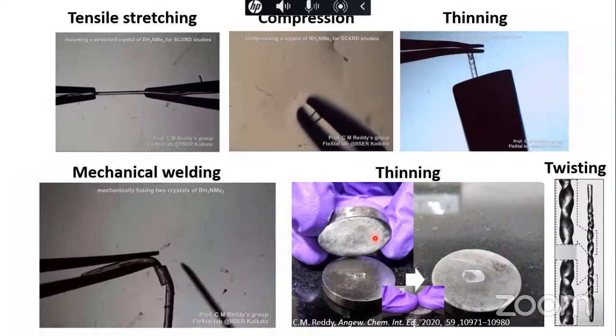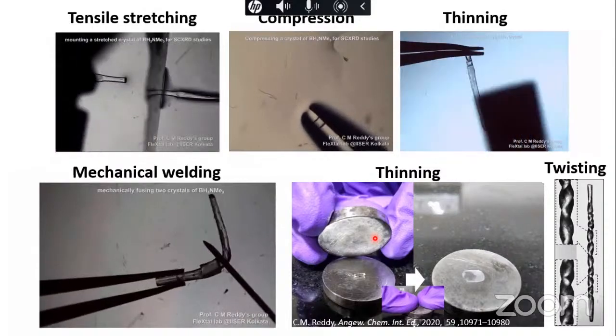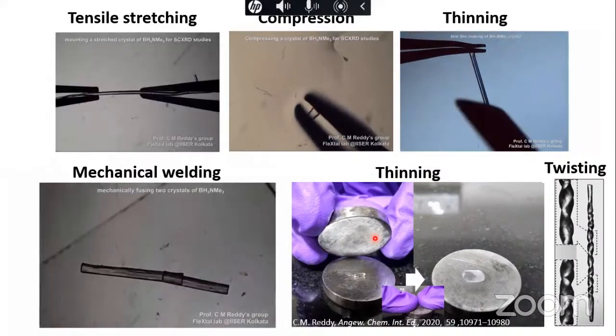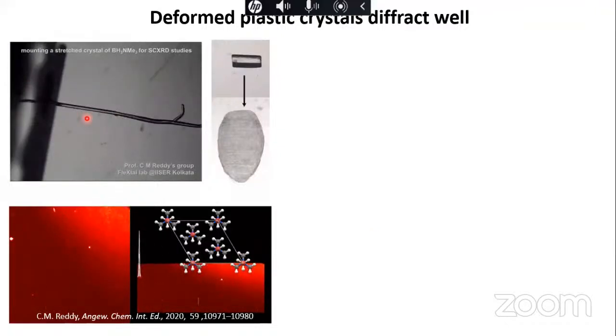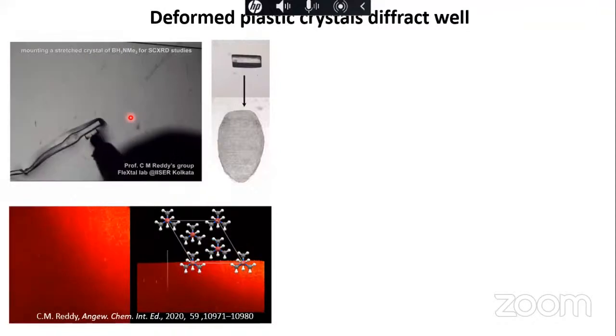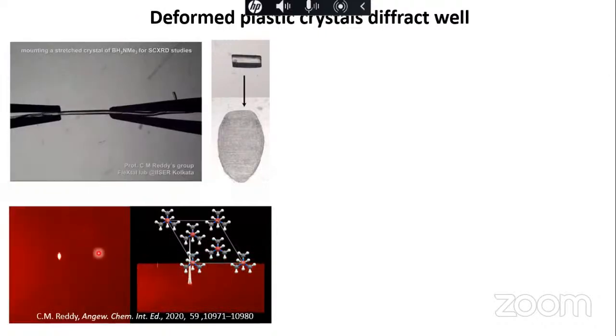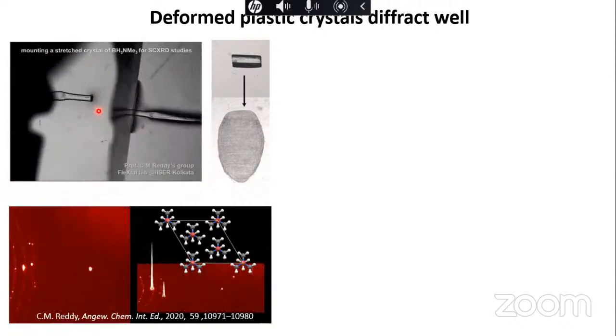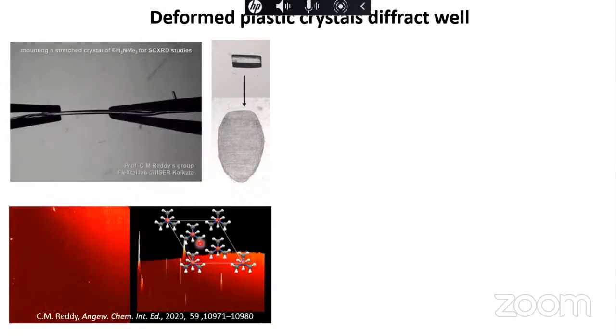You can do whatever you want with that. So in this case also they behave exactly the same. Then we wanted to see what happens if you pull these crystals, cut some portion, and diffract. So we looked at the diffraction pattern, and we could actually get a very nice diffraction pattern from these elongated crystals, and we could get the single crystal structure in these cases.